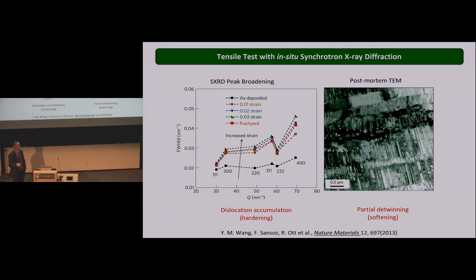Another thing that was totally awkward is that when we do post-mortem analysis of the thin films in a TEM, we find grains that are totally detwinned. There's no twin anymore. And the only way this can happen is by shearing the grain. But we did not apply any shear. It was pure tension. And again, something abnormal happened in this observation.